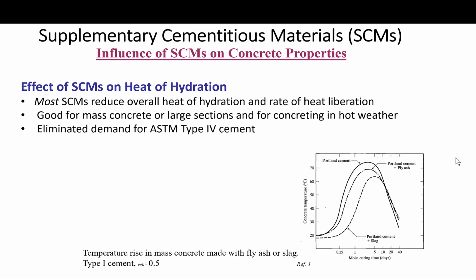As you can see in this figure, this is Portland cement alone without replacement, this is Portland cement with fly ash, and this one here is with slag. Under moist curing conditions, you can see the temperature rise with time is reduced overall. Again, the reaction is slow, so the heat rise is much lower.